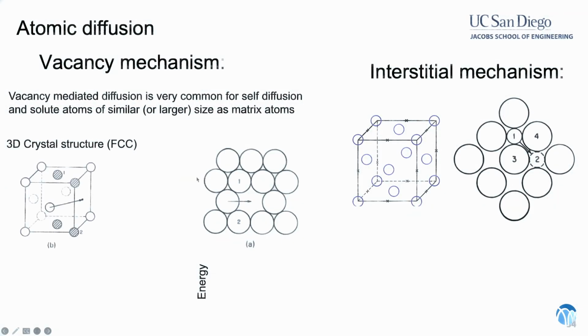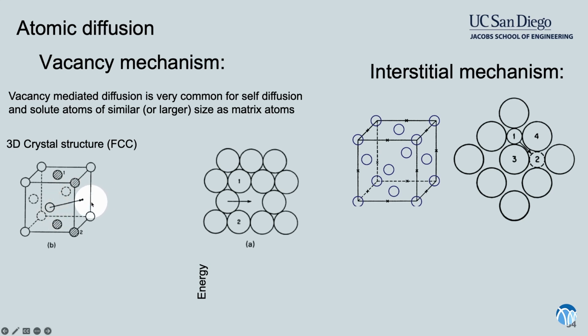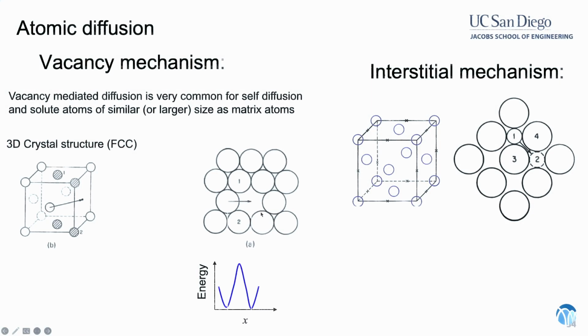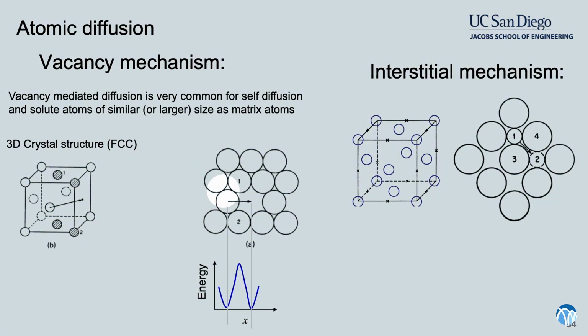Okay. Let's move on and show a little bit of schematic here. So for a vacancy mechanism, if I have a crystal structure of a typical metal, like gold or aluminum, it's face-centered cubic, and I want to move an atom from one part of the crystal to another part of the crystal. This is in 3 dimensions. In 2 dimensions, the most common way that would be done is through a so-called vacancy mechanism. You have a missing atom here, and then an atom moves over, and this is the activation energy that we were talking about. Because this atom has to squeeze in between this smaller volume, you have a high energy site here. You have to supply that activation energy. Typically, this is temperature that supplies that energy, but it can again be supplied by something like a neutron. Okay, so this energy allows the atoms to move, and now you're again at an equilibrium site.